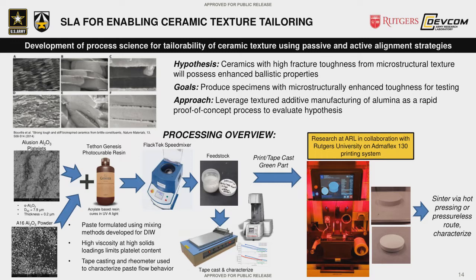So we've been using these alumina platelets along with conventional alumina powder and mixing them with a photocurable resin base that's commercially available, using the same high shear speed mixing techniques that we've been using for our direct ink writing to create the ceramic feedstock.